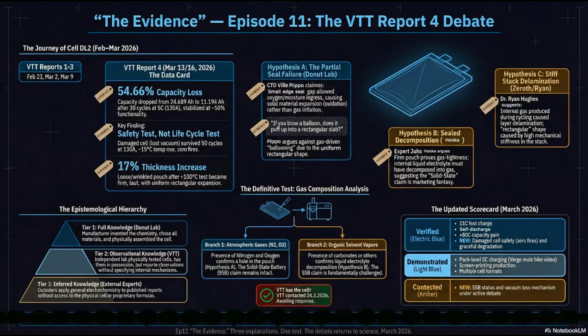Precisely. And the outcomes of this test are entirely binary. It would instantly prove who is right. Completely. If the mass spectrometer detects high levels of ambient nitrogen, oxygen, and subsequent solid oxidation products, it proves atmospheric ingress. Donut Lab is telling the truth. There was a hole and air got in. And if they find something else? If the spectrometer detects organic solvent vapors like vaporized carbonates or ethers, it proves liquid electrolyte decomposition. Dr. Heiska and the skeptics are right. It really is that simple.